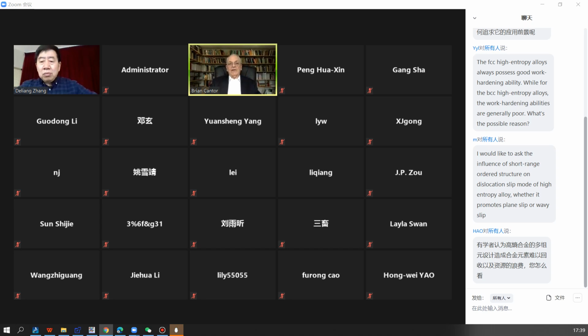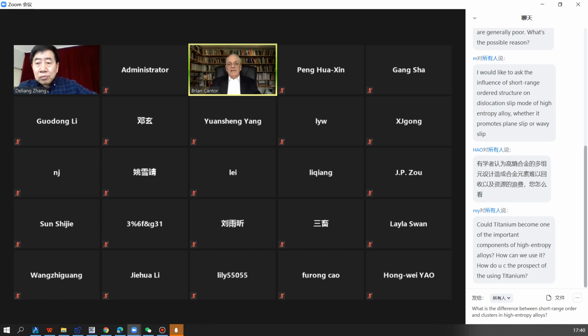People are still trying to improve the strength, and they're trying to improve the strength by traditional metallurgical methods. For the FCC materials, they still want to make them stronger, and they're trying to do things like make them have small precipitation hardening, control the strain hardening through work hardening, the traditional things that we do, but also use transformation hardening by allowing them to transform. So there are classic hardening methods being used for FCC materials, and there's quite a bit of work being done on that now. For the BCC materials, a lot less work has been done, but people are trying to improve the ductility. But they start with a fantastically great strength. There's plenty of room to back off a little bit on that and improve the ductility. So I think there are some great combinations of materials being developed as we talk, because there's so much work going on. Okay. Yeah, thanks.